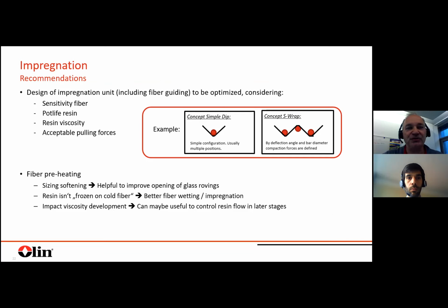Some recommendations in terms of optimization of the impregnation. So for sure, as mentioned, it's really the design of the unit itself that has to be optimized. I think it depends really on different parameters, how it can look, how sensitive is your fiber. Some fibers break at every deflection, others are really robust. The pot life of the resin, is this an issue? The viscosity, and for sure also pulling forces, which is in pullwinding usually not a problem, but you can create also pulling forces in the impregnation unit, which maybe lead, if it's too extreme, to issues.